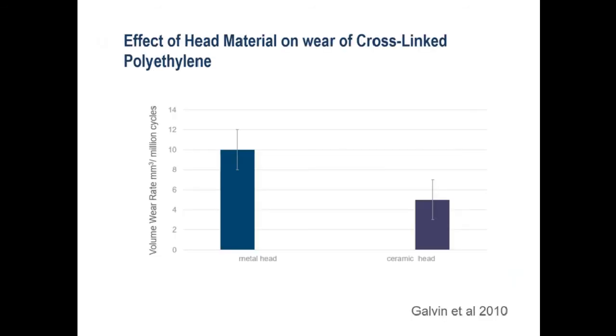Ceramic is used as a femoral head articulating against the polyethylene material. And in this slide, you can see that the wear rate of a ceramic on polyethylene material is lower than the wear rate of a metal on polyethylene material, indicating the benefits of using ceramic femoral heads compared to metal heads.